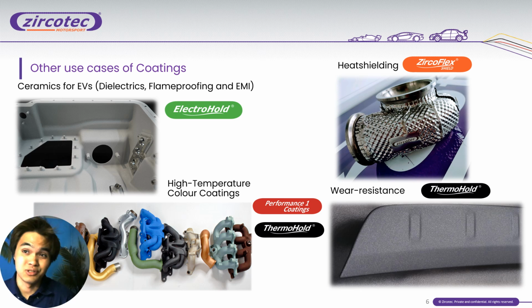The ceramic technology is not just used for thermal management. It actually has a lot of great uses. Ceramics can be used for dielectrics and, as you can see, flame proofing and EMI reduction for electric vehicles. The ceramic applied heat shield allows a better way of insulating the heat inside the part and also protecting any parts outside of the coated, heat shielded part. We also have abrasion resistant ceramics, which can protect the material from scratches, environmental damage and corrosion. Our thermal barrier coatings can also be color coated, withstanding up to around 980 degrees, which allows for better performance and also better looks, as you can see in the various colors.